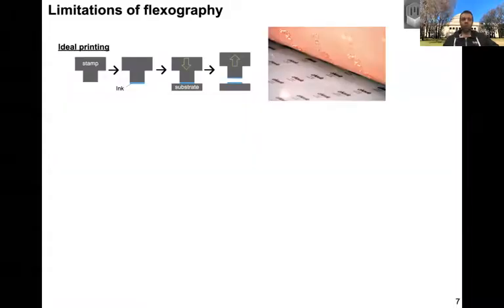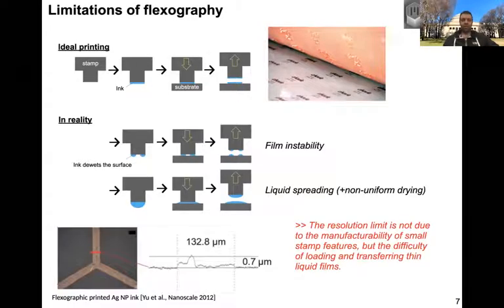So the question is, what are the limits of this process in terms of the ink transfer? And you might think ideally you take a stamp with, say, a flat raised feature, call it a micro pillar, load ink on it, have a perfectly flat layer of ink, contact that to your substrate, and then you perfectly transfer a uniform ink layer. Maybe not all, but you split the volume as you predict. But of course, fluid mechanics make that not the ideal case.